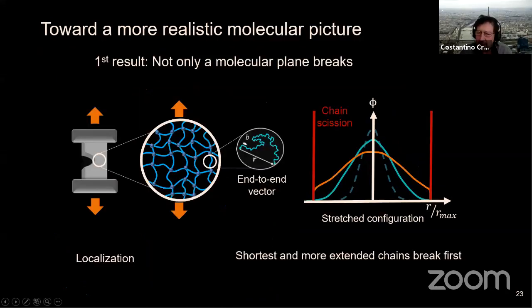Now, the fact that the rate at which you're pulling has an effect is not completely obvious. If you look at the chain level, you initially have very coiled chains, or very, very long ones that are coiled, and then you have more stretched ones. As you stretch, all these chains will change. They will get more and more stretched, and the short ones and the pre-stretched ones will break. When they break, we will start to have fluorescent signal. So this is to explain why we have this distribution.